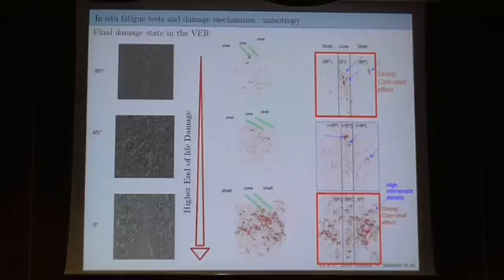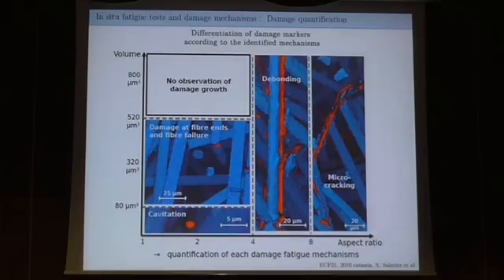You see the density here in the shell is not the same as in the core, as you can see for 90° specimens. But for 45° specimens, this differentiation is not here anymore because you have much more symmetry of the specimen. You don't have this dissymmetry with respect to the loading. So it's more symmetrical, then it's more or less the same in terms of damage, which is quite logical. But when you have this full picture, you cannot separate the whole mechanisms.